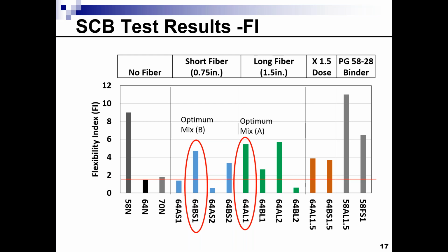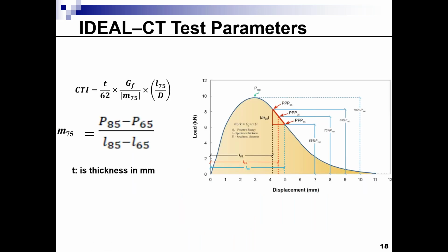Fiber A also had an improved flexibility index and cracking resistance, but the optimal, as you can see here, is when we're using the long fiber A with the dosage recommended by the manufacturer. Both of those are actually the recommended length and dosage by the manufacturers, and the two manufacturers are suggesting different lengths. So at least based on the flexibility index, their recommendations seem to be correct.